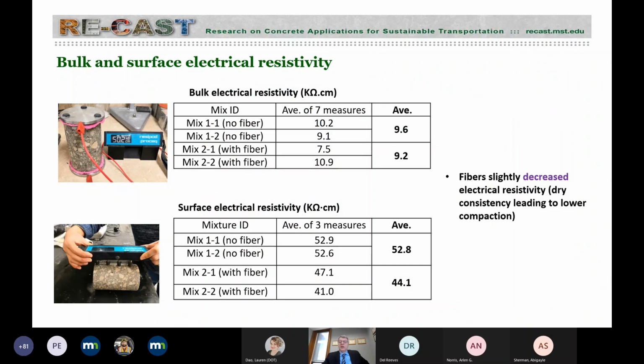The electrical resistivity, again, you see bulk electrical resistivity and the surface. We tested those with and without fibers. And you see that with the fiber, the resistivity was lower, indicating maybe some issues with the bond interface, both for the bulk and the surface resistivity. So fibers slightly decreased electrical resistivity. And we think that it's because of the dry consistency, probably lower compaction, but also the lack of good transition zone between the embedded fibers and the cement paste.